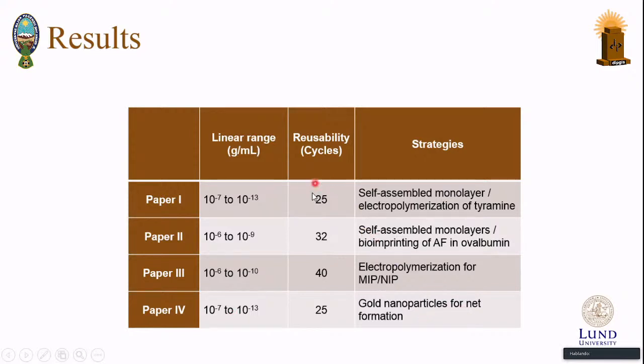We can see that the reusability differs in different papers, as in paper 1 and paper 4 we are using antibodies, and this can be affected by the regeneration solution, which is at a pH around 2. In the case of paper 2, when using bioimprinting, we have 32 cycles for reusability. This is as this molecule is more rigid when we are using glutaraldehyde. And in the case of molecularly imprinted polymers, we have 40 cycles, as this molecularly imprinted polymer is a synthetic polymer and can be used in harsh conditions when regeneration is used.